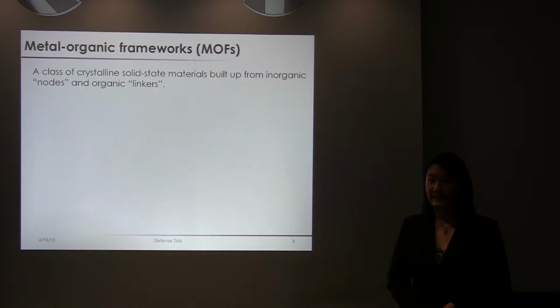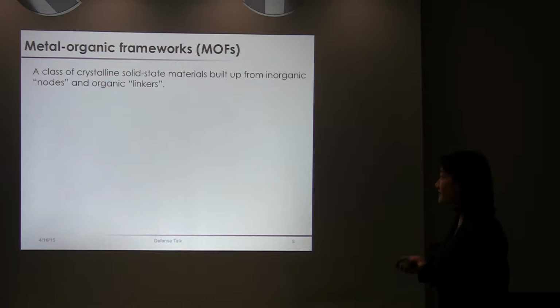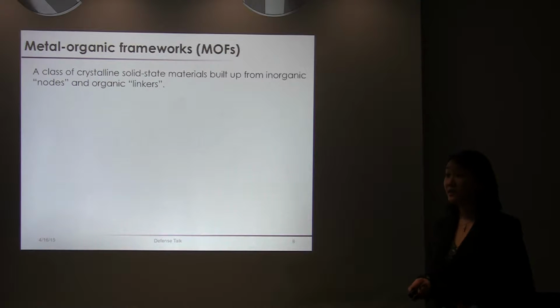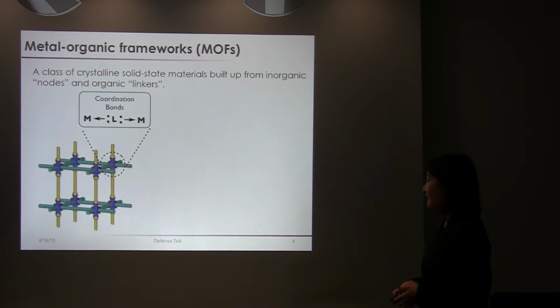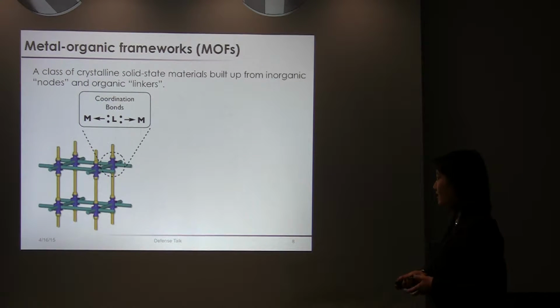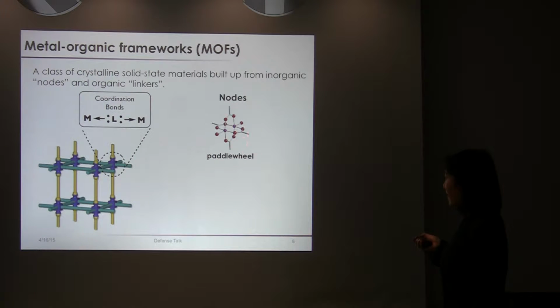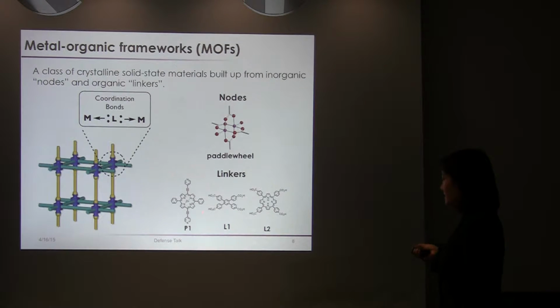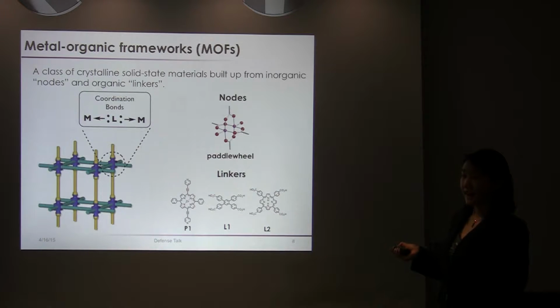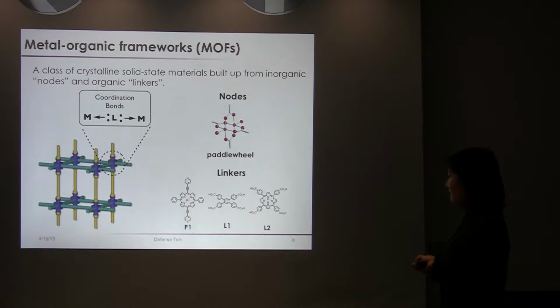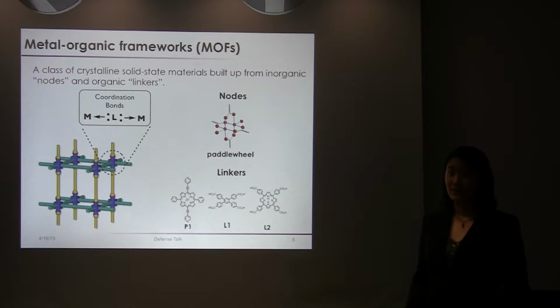Right. So one potential material that I'm working on is what's called a metal organic framework, or MOF. Essentially, it's a self-assembling crystalline solid-state material that is composed of metal ions that are interconnected by organic linkers of moderate strength. And essentially, ligands are generally bound to the metal ions by a coordinate covalent bond. Examples of nodes include paddle wheel units, such as this paddle wheel unit that includes 2 zinc ions interconnected by 4 carboxylate linkers, as well as linkers, including this P1 dipyridyl porphyrin-based linker, and these 2 tetracarboxylate linkers, L1 and L2. So what this tells us is metal organic frameworks are readily tunable structures, since there's a spectrum of different organic linkers, as well as inorganic nodes that can be used to assemble these materials.